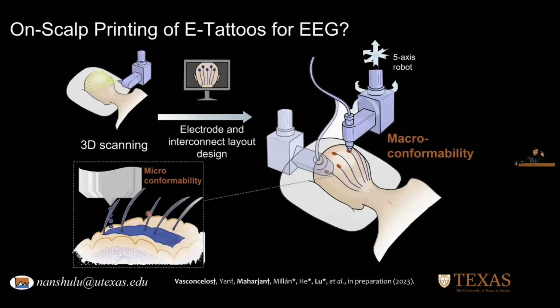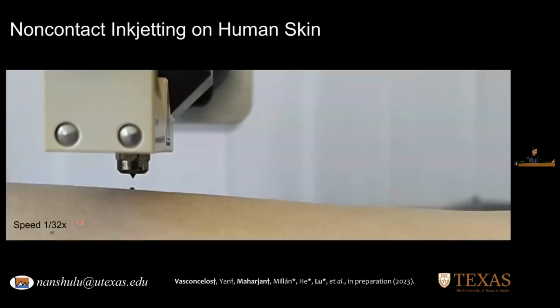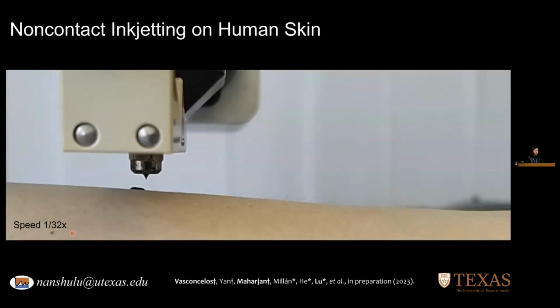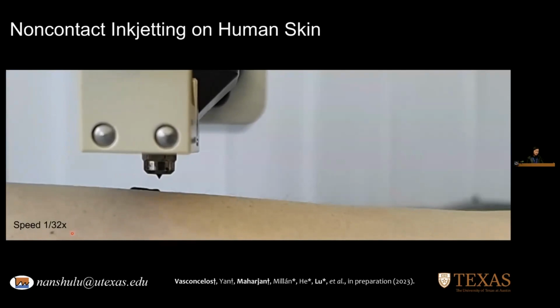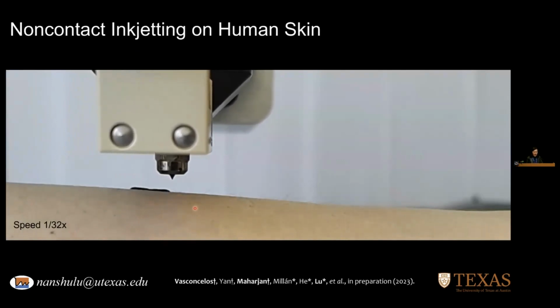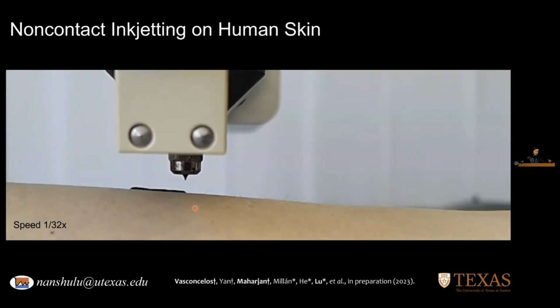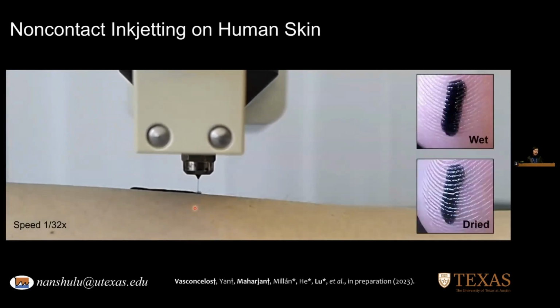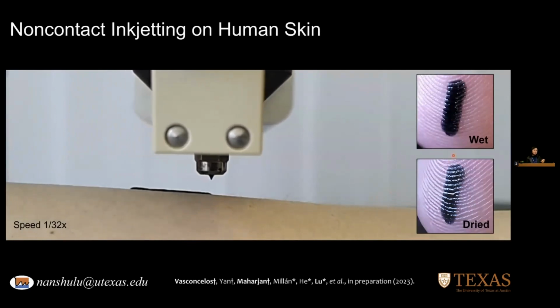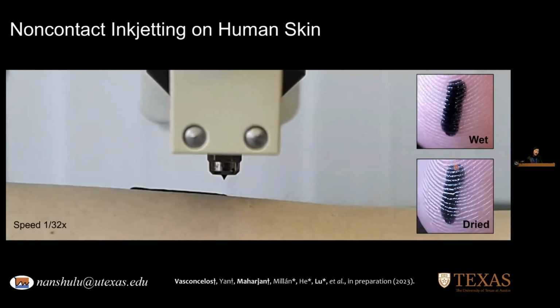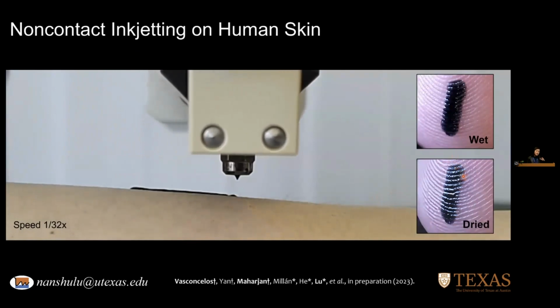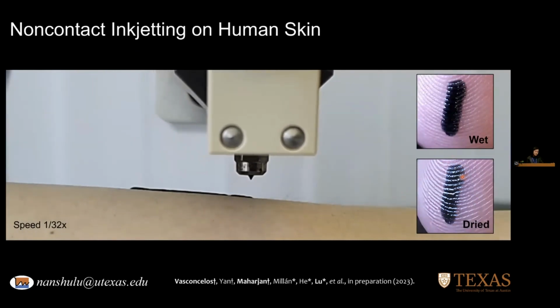Even though there are hairs, currently only works for buzz cut, the inkjet can still jet through the hairs and wet the roots of the hairs and conform to the microscopically rough skin surface. This is a slow motion of the non-contact inkjet printing of a conductive ink that can jet through those micro hairs on the arm. And as jetted, it's a liquid. It can conform to whatever surface roughness we have. But after 15 minutes, this ink can self-dry and cure under room temperature on the skin, and it becomes a thin conductive film, completely dry, of a thickness around 20 micron.